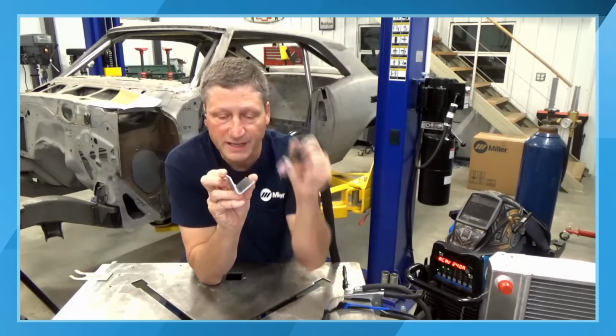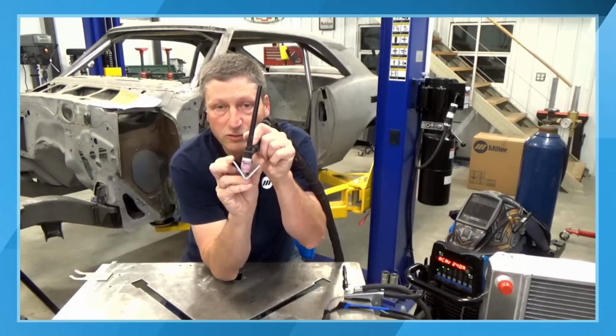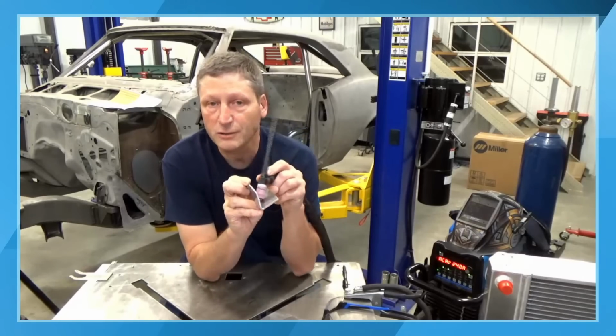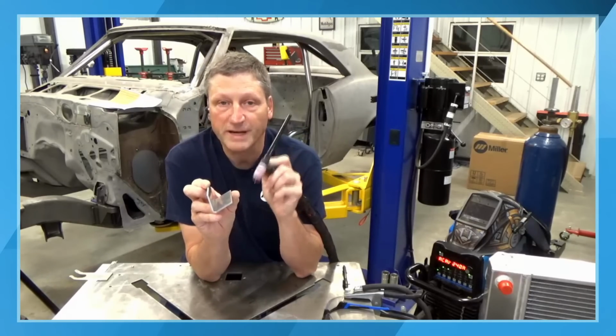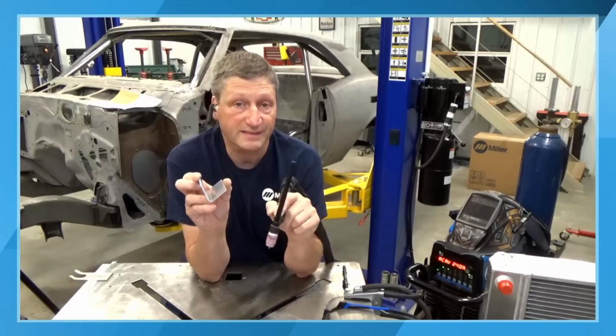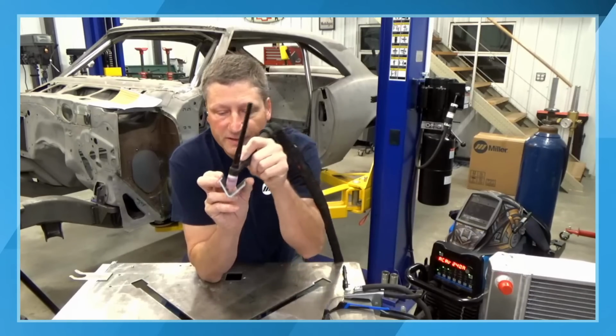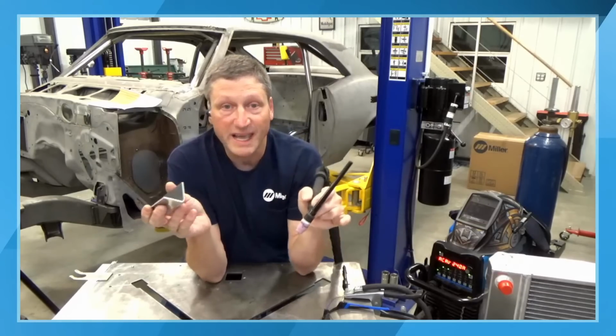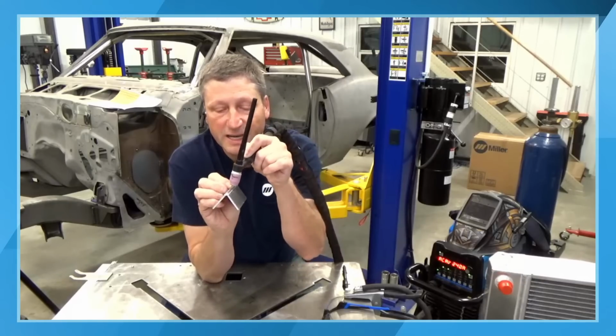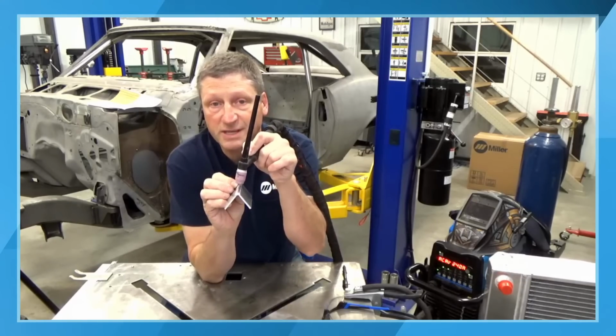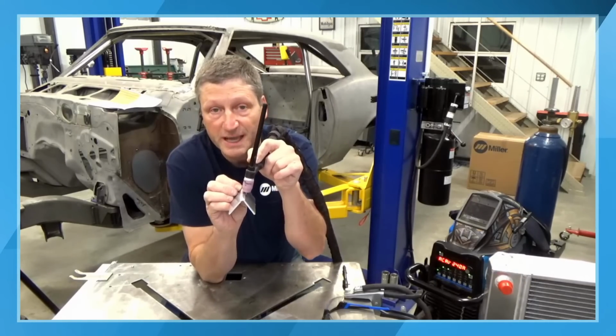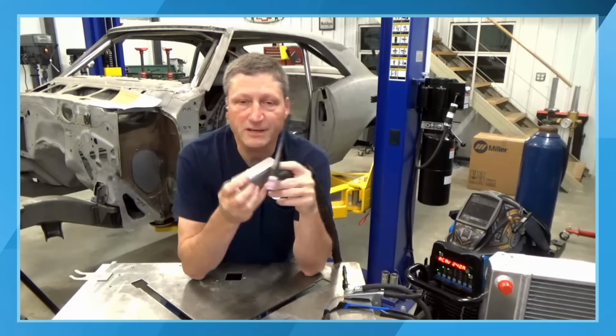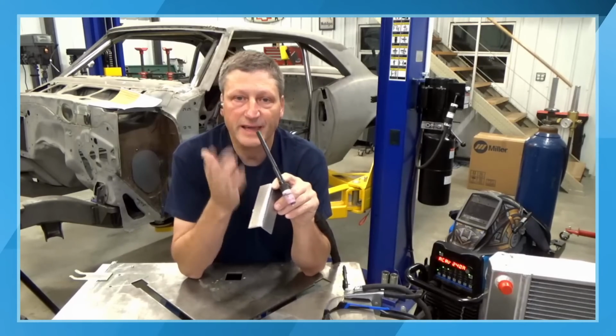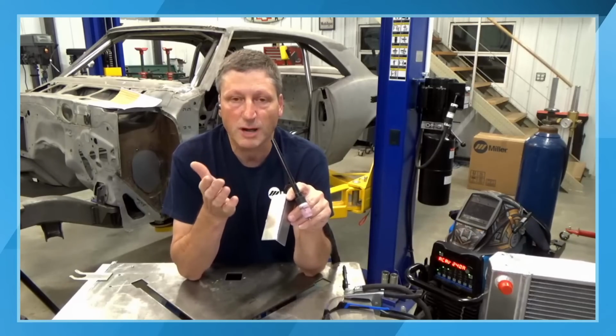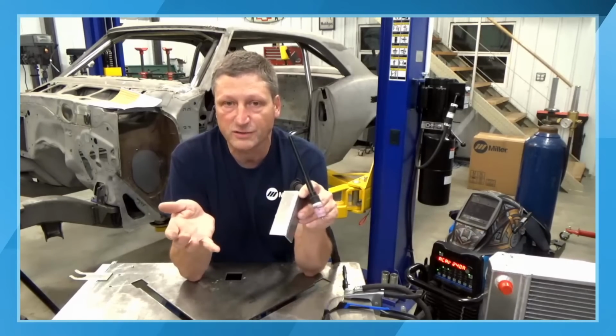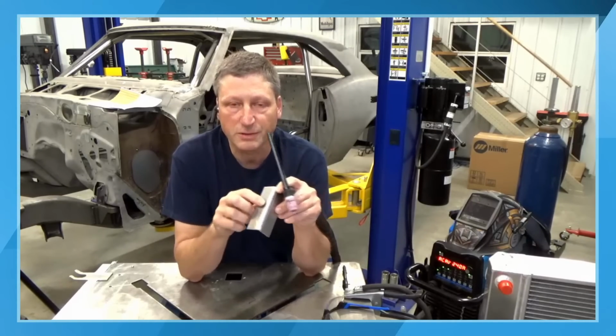If I'm welding inside here, now the base metal is closer to the tungsten, so I can increase my balance and spend more of my time in the weld portion of the AC. So in this case, I would set my balance up to maybe 80%. On this side here, I'd have it down to around 71, 72, something in that area. But the idea is make sure you do see a little bit of that etching. That way you're going to make sure that the cleaning is proper so that the edges of the weld, which is called the toes of the weld, properly fuse to the base metal.